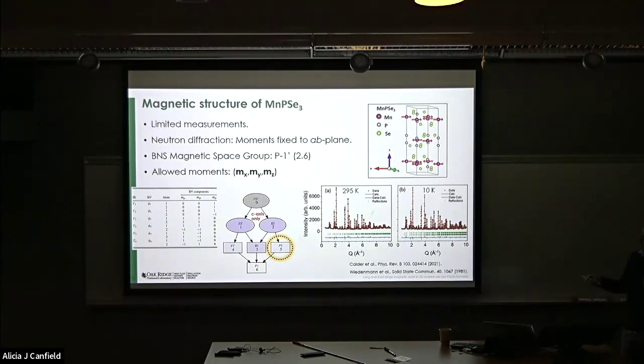MnPSe3. There were limited measurements. There was one report back in the 80s, I think. So we collected a bit more data, tried to determine the magnetic structure. What we found was it was consistent with spins being in the AB plane, so within the layers. If you start to look at symmetry analysis and go down to what should be the maximal subgroups, down here R-3, these should have spins pointing along the z-axis. So you actually have to go to quite low symmetry to reconstruct the magnetic structure you see, which is kind of interesting. So maybe there's a bit more to this story as well.